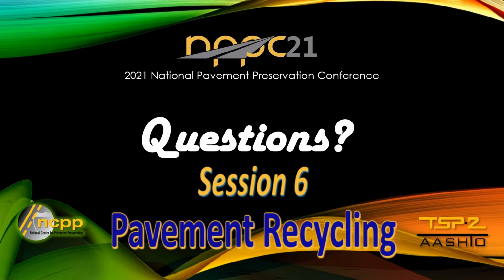It's a very fair question, and I've seen that segregation can be an issue. Generally, it has a lot to do with the instances I've seen. It might be resolved with some of the configuration on the paver screed, for example. A lot of times we see segregation out at the edges or even in the middle where we have to change the way the material's flowing under the screed.